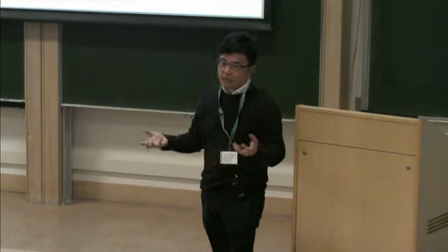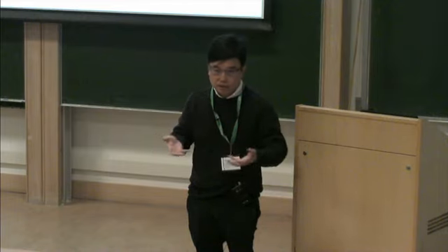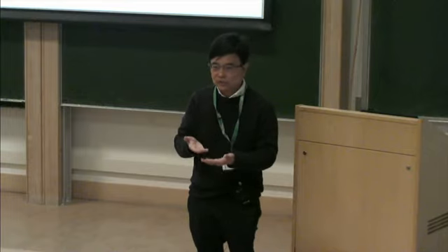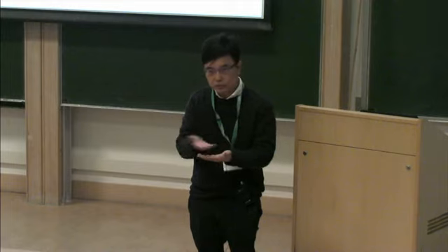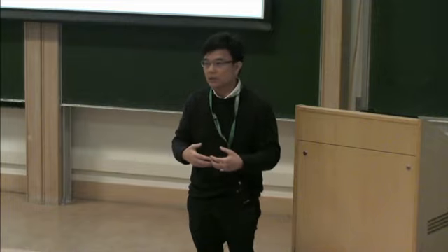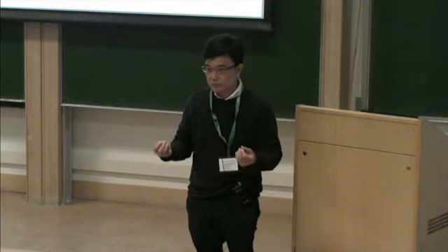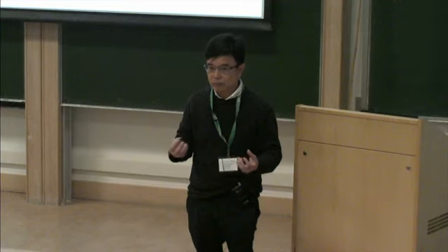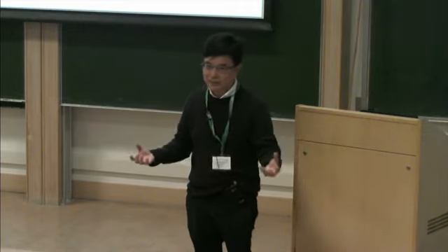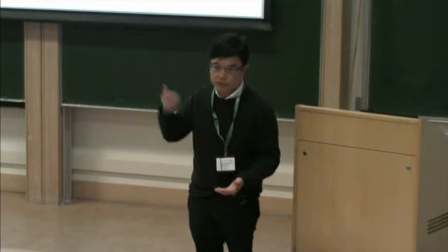Well, if you look at the plastic deformation of ice, ordinary ice is hexagonal. So for example, I discussed the significant elastic and plastic anisotropy between dislocation motion on the basal plane and dislocation motion on some harder planes. In metals, if you have cubic structures, you have many slip systems. So the deformation mechanism is different, I guess. We are looking at different crystals. Of course you also have hexagonal zinc crystals, for example. But ice also exists at very high homologous temperature under ordinary circumstances.